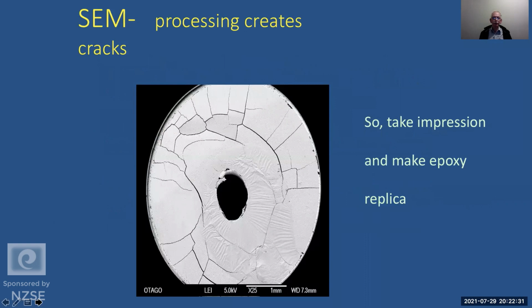And the thing about scanning electron microscopy is once you put a specimen in the microscope, it's ruined, you can't do anything further with it. It desiccates, some cracks. And so the way this experiment was conducted was that at each stage we took an impression of the root face and we made a model of it with epoxy resin.